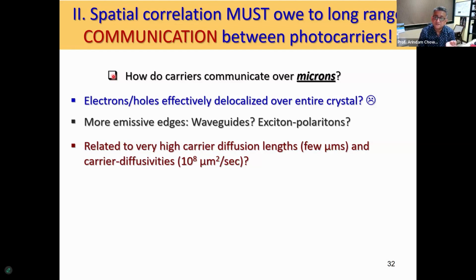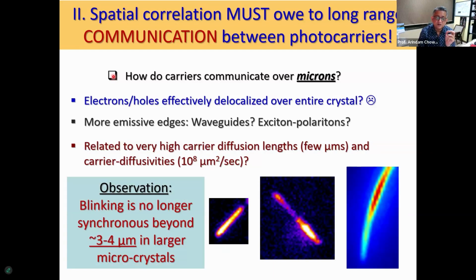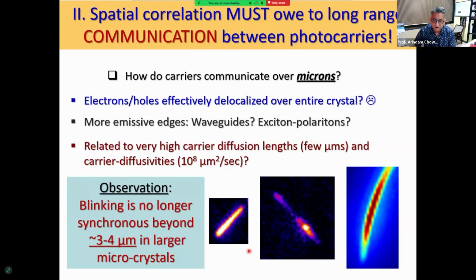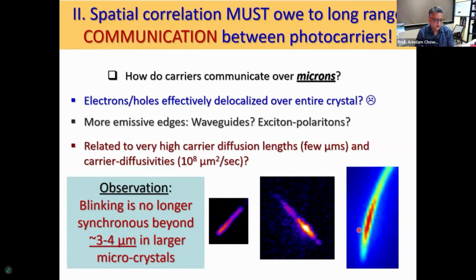And the carrier diffusivities are also high. Our experimental observation was that blinking is not synchronous beyond a few microns. And this is just an example of rods. On the left, you see a synchronous blinking. On the right, you see blinking or fluctuations that are happening, which are spatially not really correlated beyond a certain length.